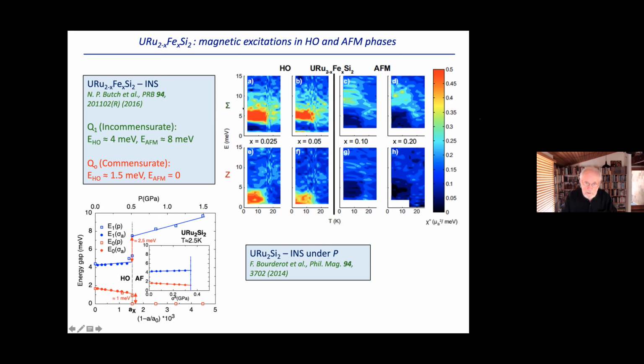So these two are in the hidden order range. These are the excitations, these red regions in here. And then when you get into the antiferromagnetic phase, the intensity is much less, but you can see the excitations up here that are around 8 meV. And then for the commensurate excitation, it happens at about 1.5 meV in the hidden order range. But then when you get into the antiferromagnetic range, remember it has the period doubling along the z-axis. And even though we don't know what it's due to, it then basically becomes the antiferromagnetic order when you get into the antiferromagnetically ordered phase, and the excitations just disappear because you have this long range antiferromagnetic order.